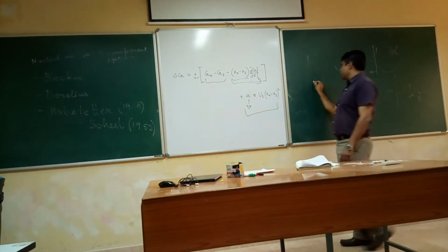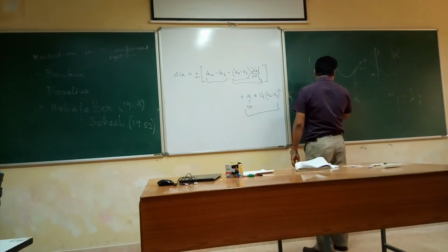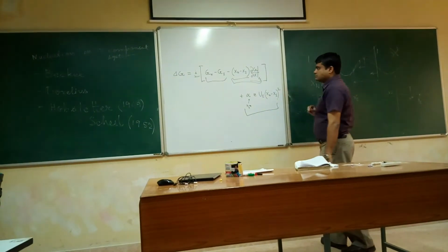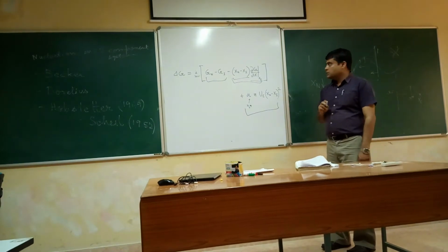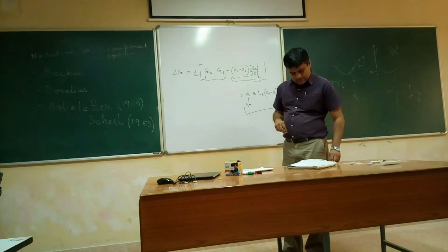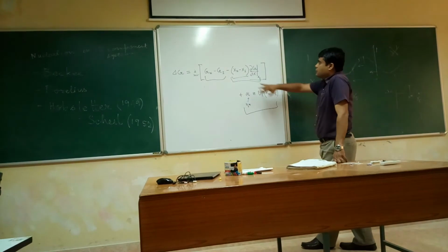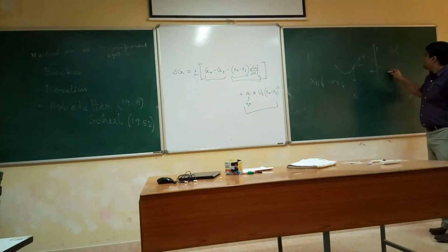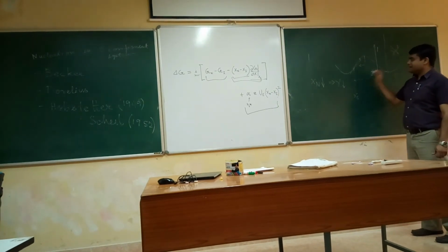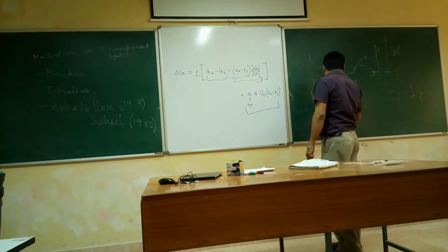As Xn, the composition of the embryo, goes down, your gamma or surface energy term goes down. But your delta GV is maximum here, and as Xn goes down, the mod value of delta GV also goes down.